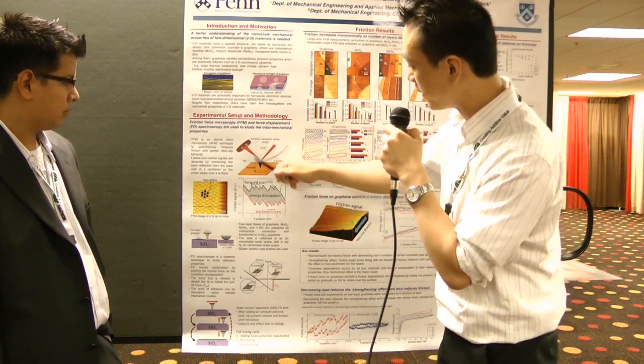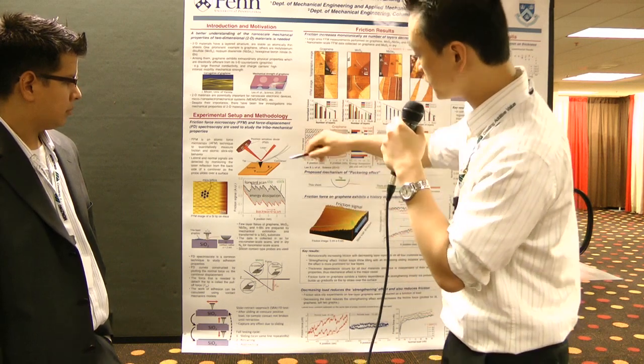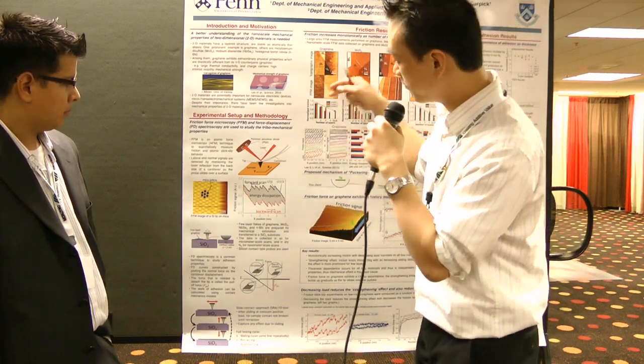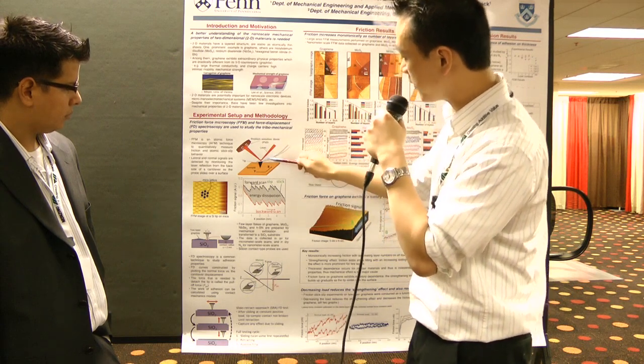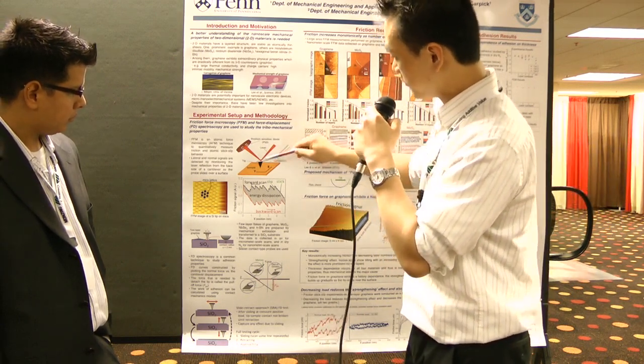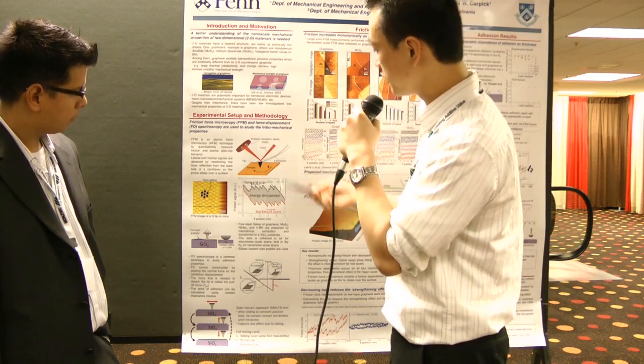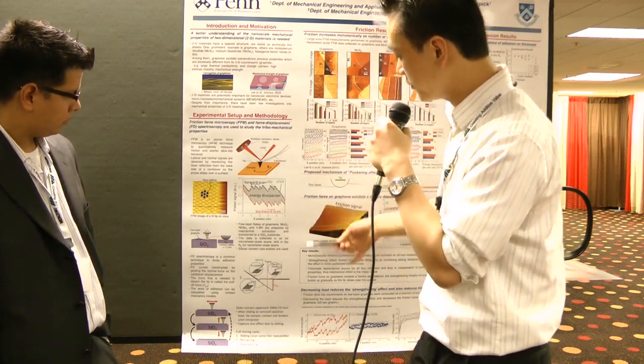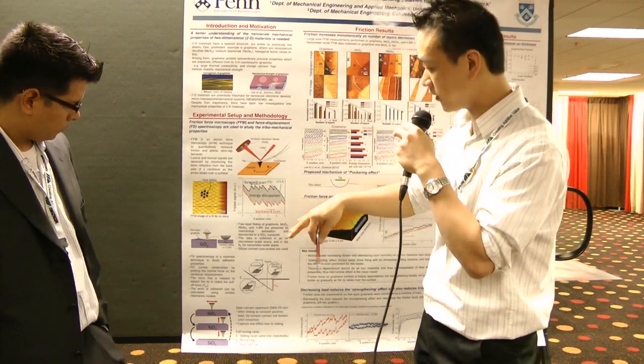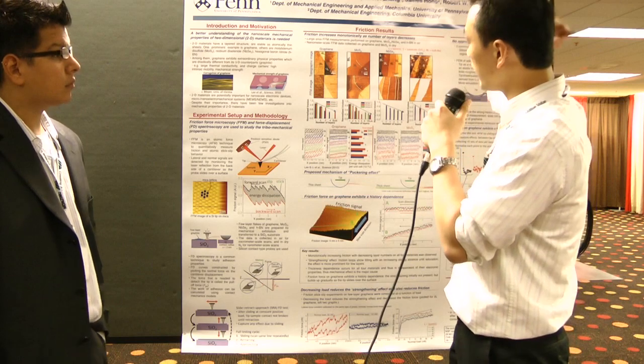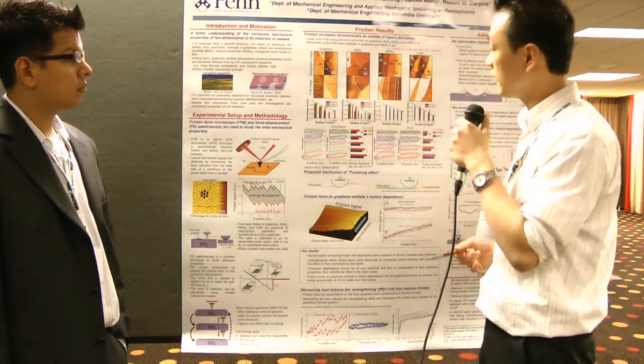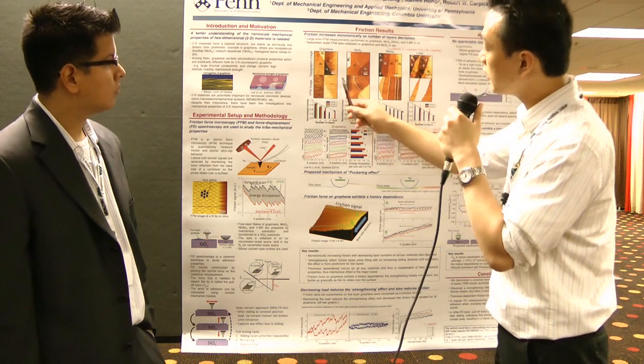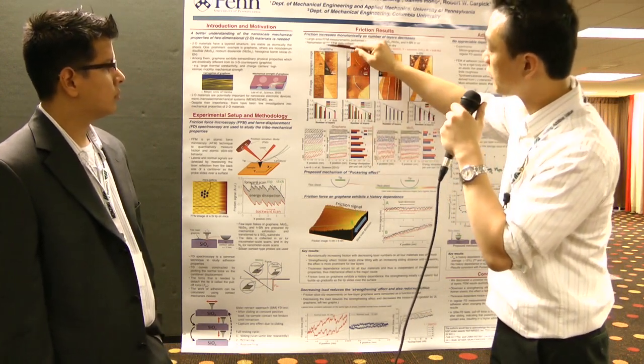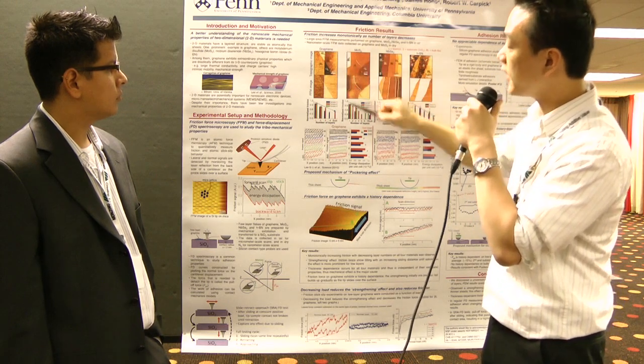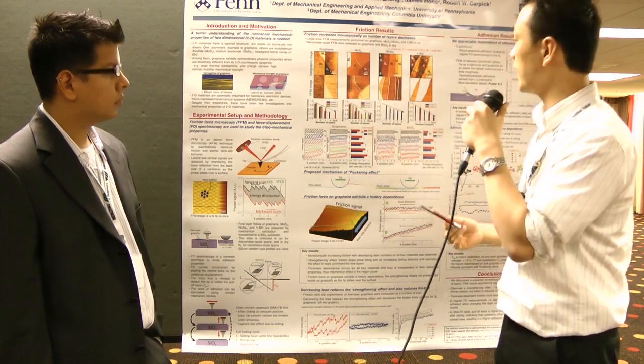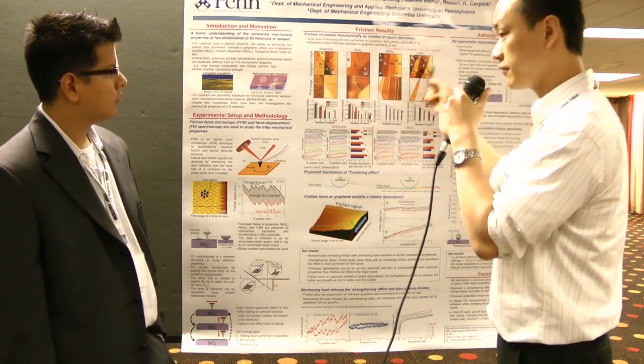As you could see here, the working principle of AFM is using a cantilever to scan over the sample, and by shining a laser on the backside of the cantilever, which is flexible, you can measure the topography, you can measure the friction, and using the same technique, we can measure the adhesion of the surface. So we made a few discoveries, and one is that the friction is layer dependent. The higher the layer number, for example in this case four layers, we have the lowest friction, and that's universal for the materials that we have studied.